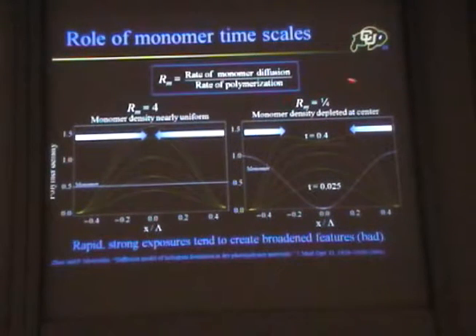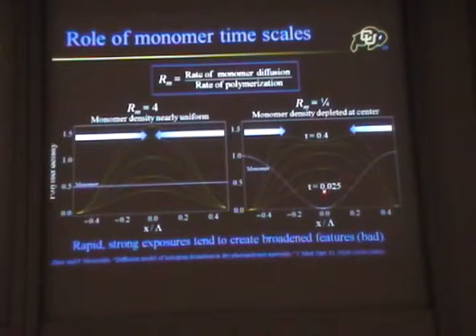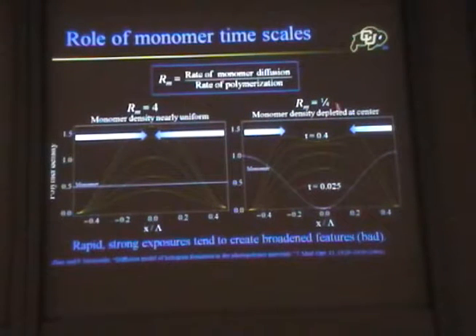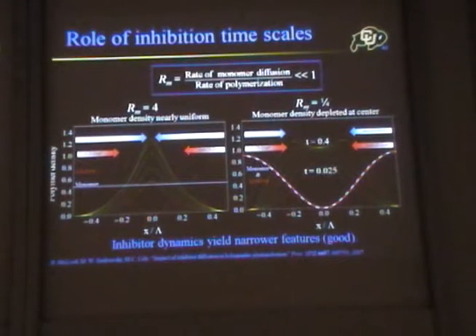If I change this number by changing the diffusion coefficient of my material, or by increasing the rate of polymerization—which is turning my laser intensity up—I can dial this around in many ways. If I go to the other side of one, diffusion is slow. As time goes on, I begin to develop holes in my monomer. The polymer starts to grow, but then gets broad and flabby, eventually developing that double lump I showed before for the hologram case—the walls. Monomer is diffusing in but hiding out on the edges. It turns out exactly the same kinetics happens to the terminator.